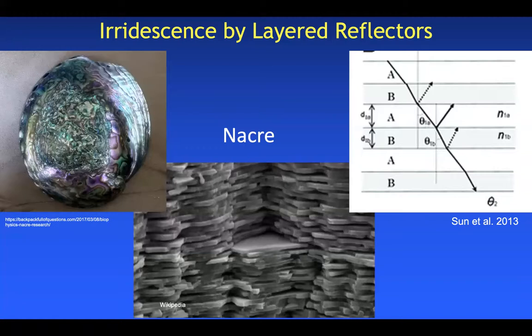Many different kinds of clamshells actually consist of thin layers of a calcium carbonate called aragonite, and they are glued together by a combination of proteins and polysaccharides, and they have a very, very consistent thickness to these platelets. They're transparent at this thickness. And so light rays are actually reflecting off of each one of these layers. And again, it's just this lambda equals 2d sine theta kind of formulation that gives rise to iridescence. And as a result, pearls have a kind of iridescence, and abalone shells do as well.